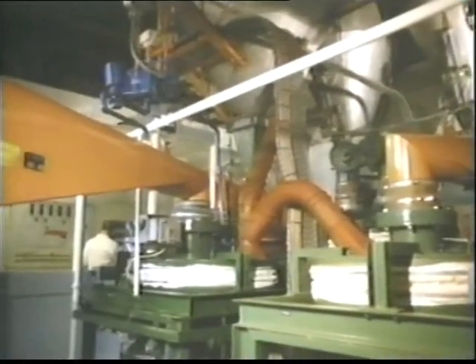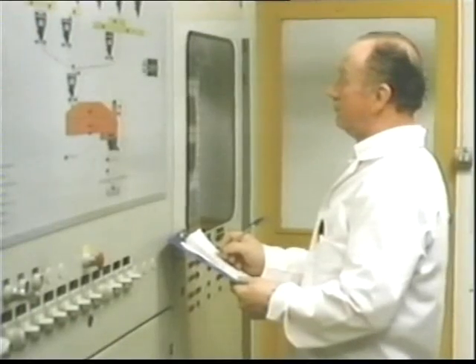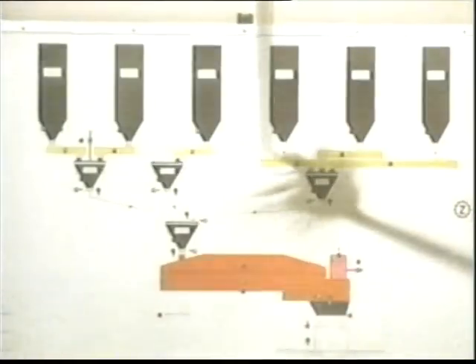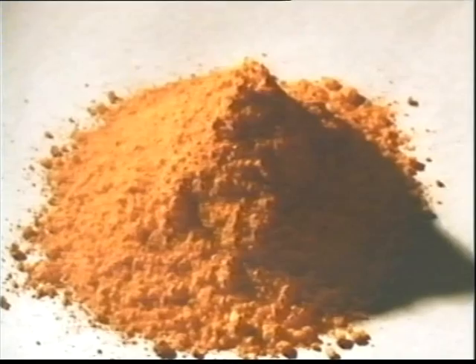There's one part of the Waterford process where human skill and care have been replaced by high technology. The mixing of the raw materials is the one area in which computers have improved on age-old methods. It's the unusual weight and softness of Waterford crystal that allow it to be blown and cut in such a special way. Now there is absolute precision in the mixture of the ingredients: sand, potash, red lead. But when these are mixed, there is one further ingredient — cullet — crystal that has already been blown and then crushed.